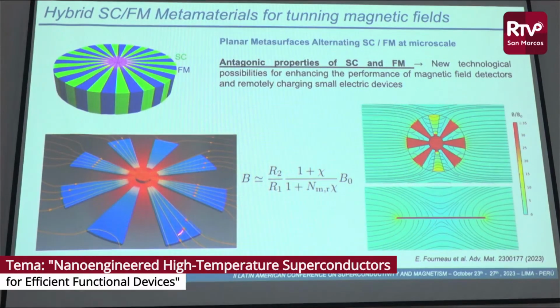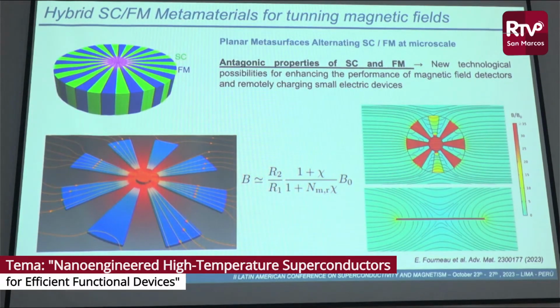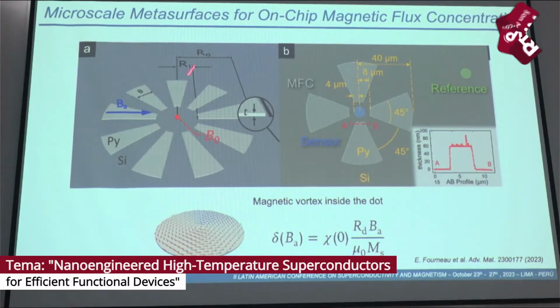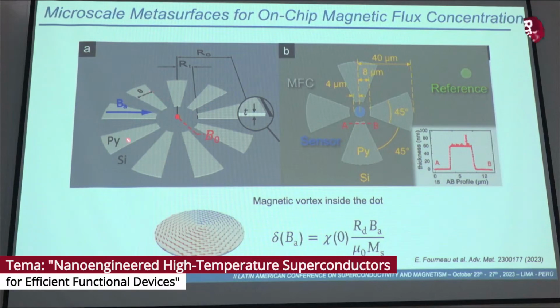The magnetic field inside of this structure would be amplified by this fact, and this can be optimized. And in the experimental system, what we have is this flower-like structure, which has been made of permalloy, in this case without the superconductor. And what we put here inside is the detector, which is a ferromagnetic dot. And by creating vortices in this ferromagnetic dot, what you could do is to track the magnetic field inside this structure. Since the position of the center of this vortex is linear with the magnetic field, by tracking this position, one can see what's happening inside of this concentrator.